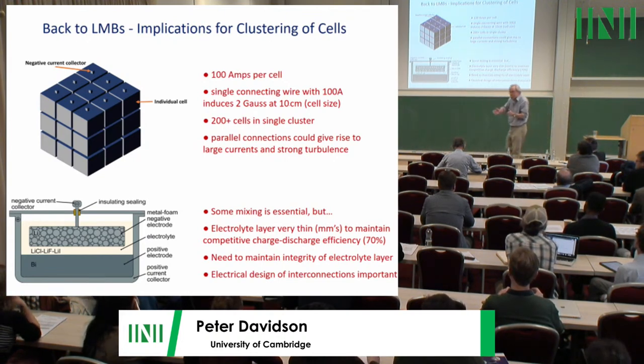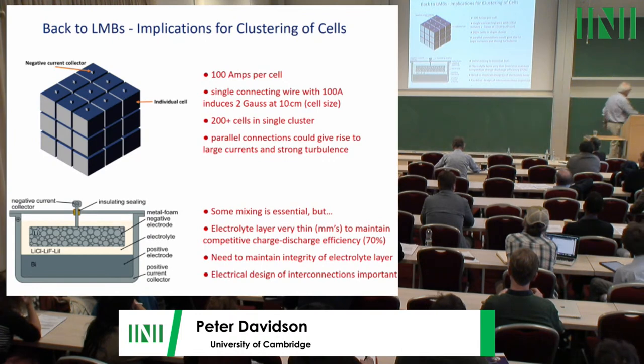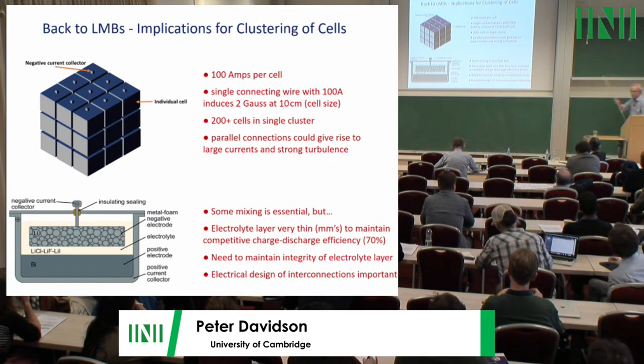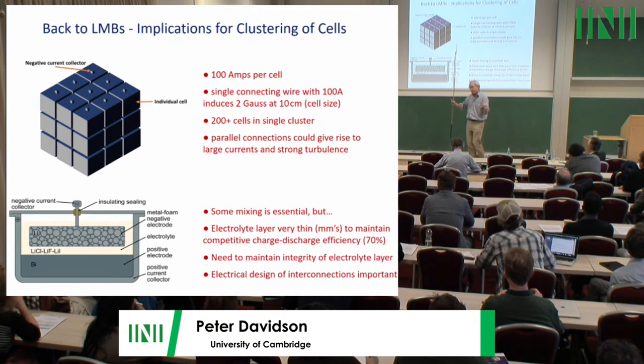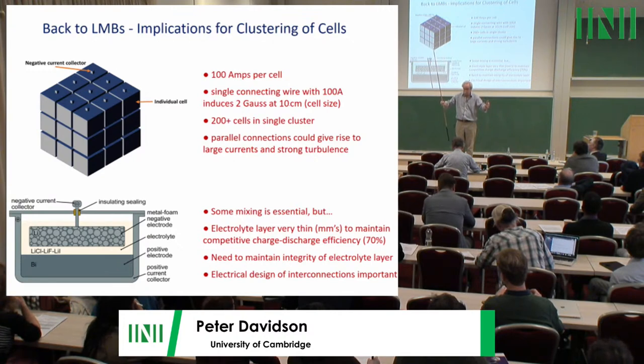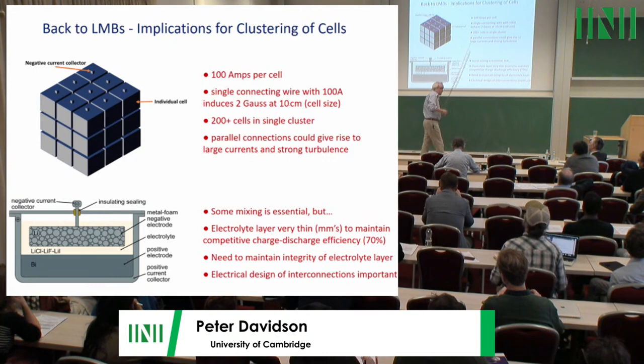So my sense is, but I should ask Don, my sense is this is a very highly constrained problem. If you think about the discussion between him and Norbert about the seals, I think you hinted that you spend an enormous amount of time just fixing this. This is a highly, highly constrained problem. You have to get the electrical design right. You have to get the efficiency right. You have to get the fluid mechanics right. You have to get the thermal design right, because you want these things to stay at 500 degrees plus or minus a bit. And you're getting that, as you pointed out, mostly from the ohmic heating of the electrolyte, but you don't want that heating to be too large, otherwise you're out of business. Your efficiency isn't strong enough. So this is a highly, highly constrained system.